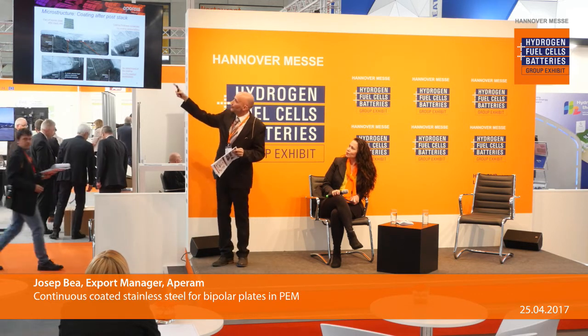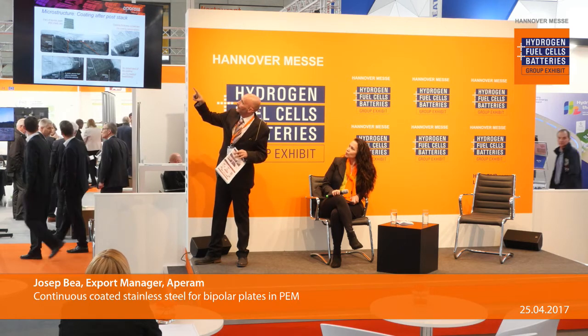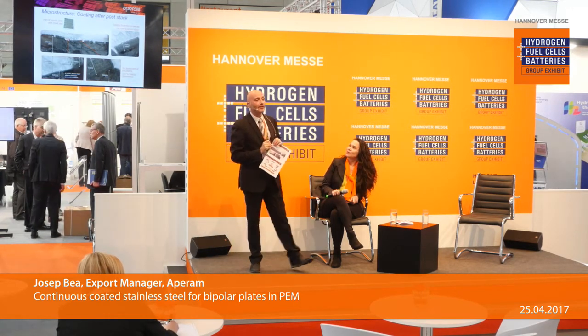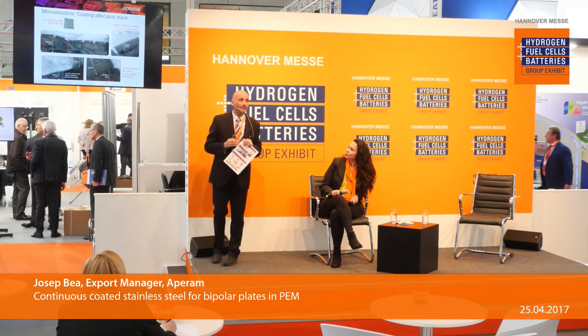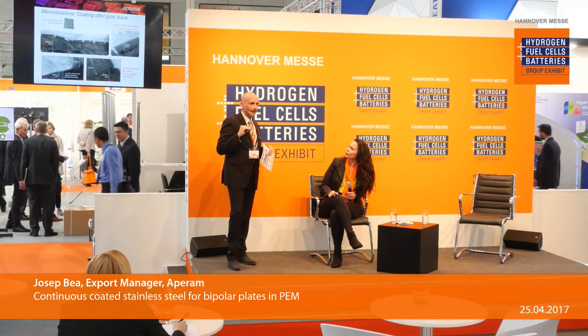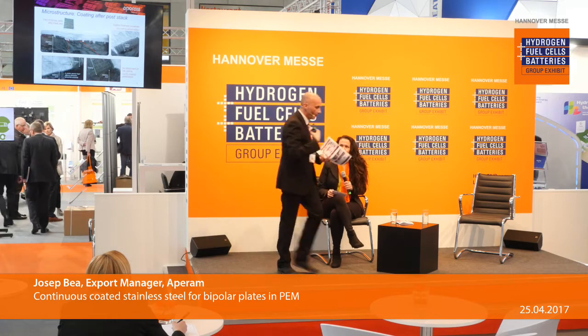Yes, but on the other hand, you will see here that the coating is conserved, so there's no coating consumption. We still have 100 nanometers of deposition. There's no detachment of the coating. We see it here. There's no fuel cell medium penetration either. And which is very important, what happened with corrosion? Corrosion, as I already said before, we have a passive layer. This passive layer is going to be rebuilt, as we see there, in order to protect the stainless steel against corrosion. And this is how we are answering this problem. It's always the same question: what's happening after?